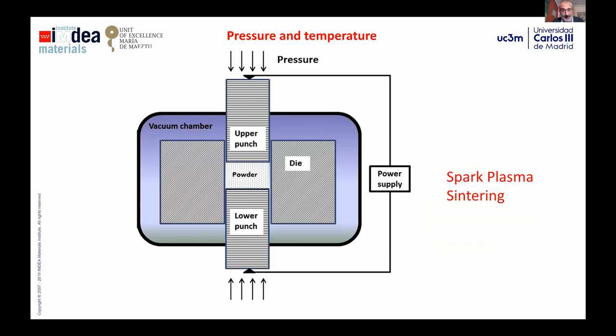The most well-known is spark plasma sintering. In spark plasma sintering, you put the powder in a die and you apply the pressure with an upper and a lower punch. Usually we have to use dies and punches of graphite in order to allow the current to pass through the powder, and we apply a current through the powder, and by Joule effect we are heating the powders in a very fast way, and we can reach the sintering temperature quickly, and we don't need such long periods to reach full density in this material.